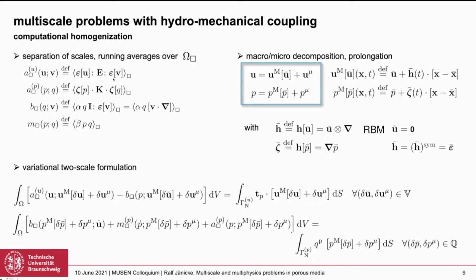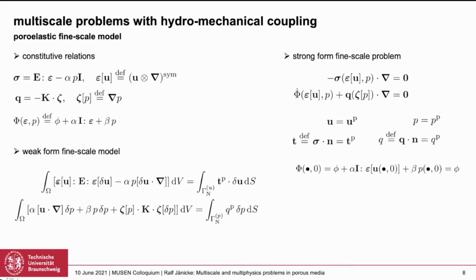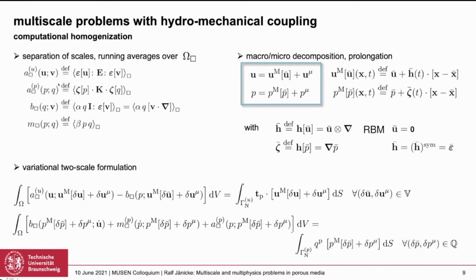We introduced the separation of scales by defining running averages, which basically means that in my global equation, which is, of course, in practice, a point-by-point integration, I interpret each point, material point or integration point, depending on if it's continuous or already discretized, as having an environment of surrounding material, and that's my RVE actually. So in each point I attach an RVE, and in each point I integrate over the RVE. That's expressed by these running averages, where I have these angular brackets representing volume averaging, defining those operators or functionals. Then I have this communication, which I call prolongation of the macroscopic field to the subscale problem.